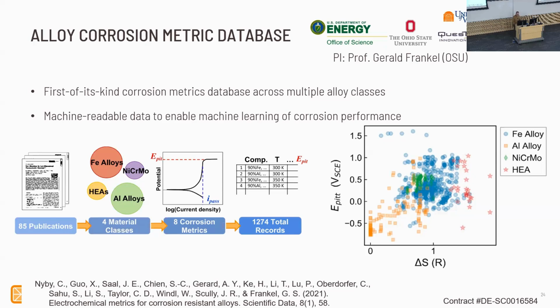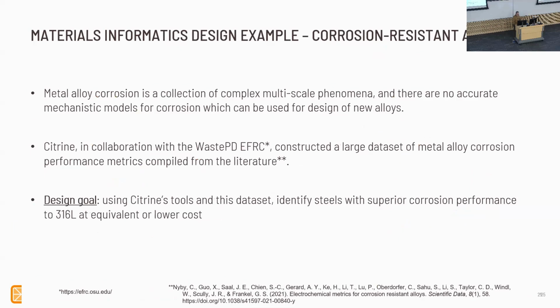for the alloy community. But you can see that various aluminum alloys tend to be very pure or very low alloy, and then iron and nickel chrome moly type of alloys also tend to be kind of in the middle. So this is just meant to show off the range of the data and what the scale of this pitting potential looks like. But now we can actually design a corrosion-resistant alloy if we have a data set like this.